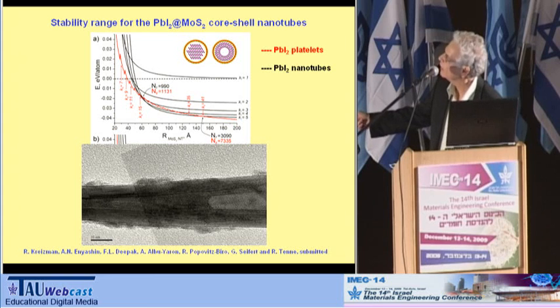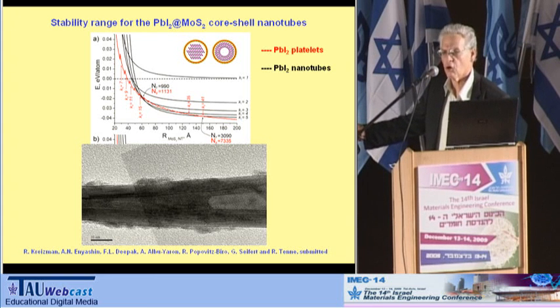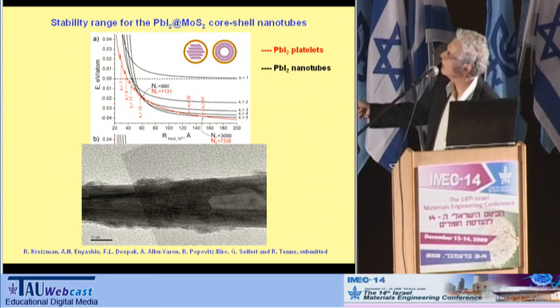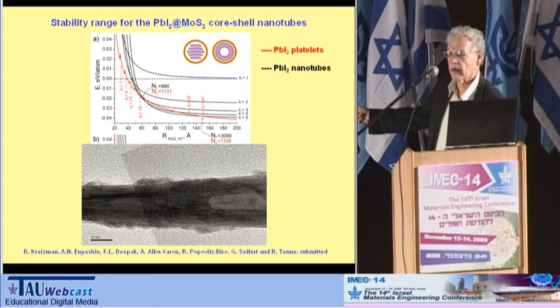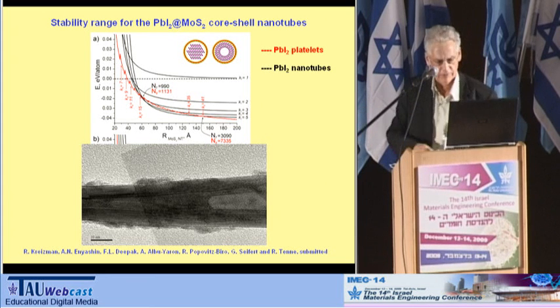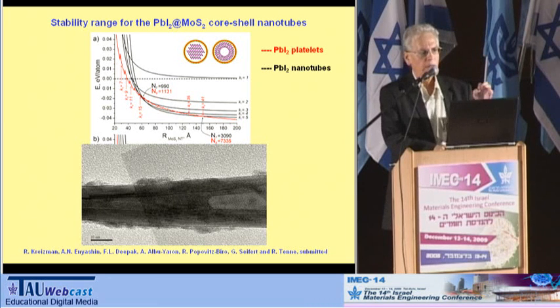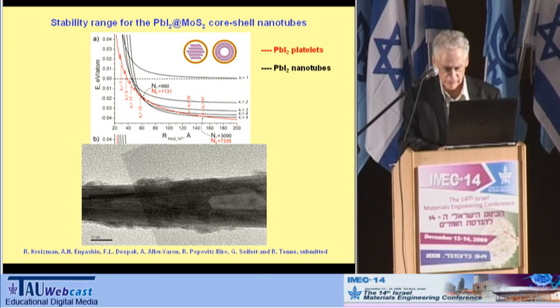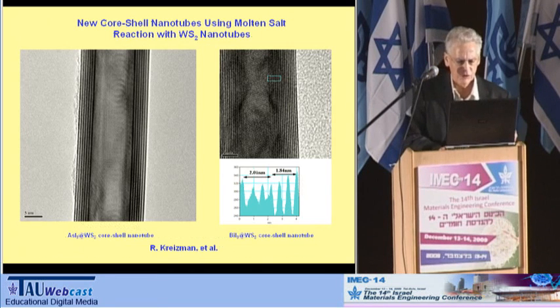So here you have a smaller constriction of the inner core. You have platelets, and when the core becomes larger, the nanotubes are preferred. So this shows that we can compare quite quantitatively between experiments, see the comparison between experiment and theory, and get very good agreement between experiment and theory.